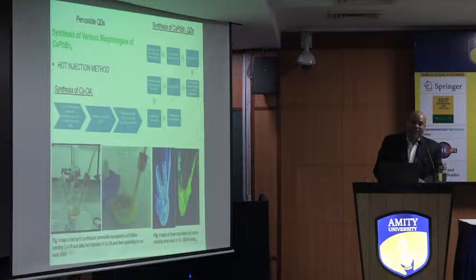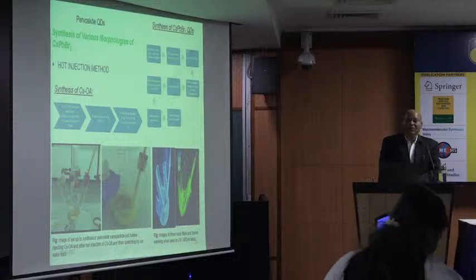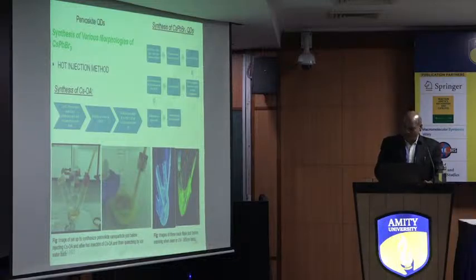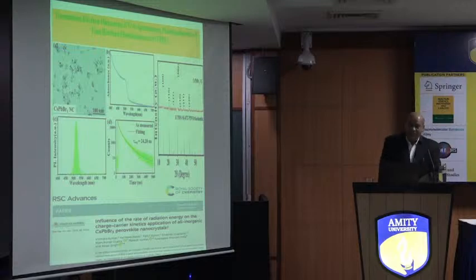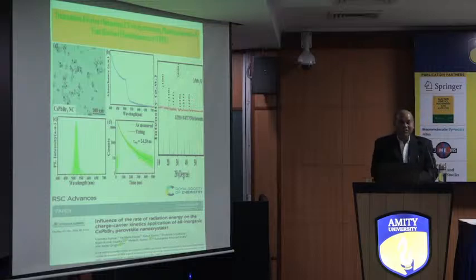Now we prepared some new perovskite quantum dots. These are some new things here. We synthesized them using oleic acid, as you can see here, and put it through some method. Then we glow it, and these things are coming. I want to show you the TEM images, which are showing very good hexagonal shapes here. This is the absorption spectra, where you are getting a peak. And the PL spectra is showing a very sharp peak at about 500 nanometer wavelength. So this is the green emission coming here.